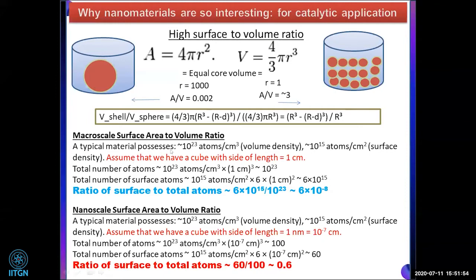And we now calculate. A typical material possesses 10 to the power 23 atoms, and that is equivalent to 10 to the 15 atoms per centimeter. And same thing here, we do the same calculation as we did before, calculating the number of atoms present in the bulk and at the surface. For the bigger particle, the 1 centimeter cube, the ratio of surface to total atoms is 6 into 10 to the minus 8.